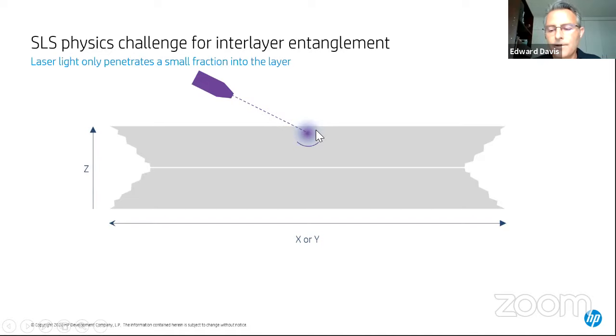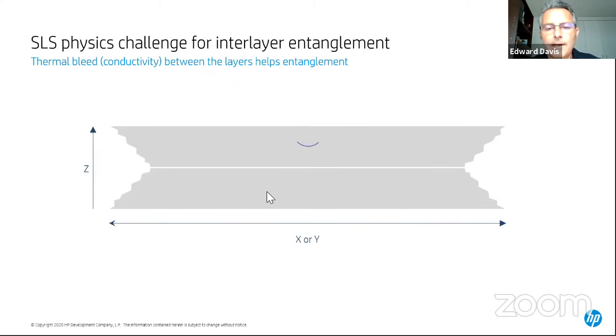Now, the fact of the matter is the laser only penetrates into the layer about 10 microns, and the layer thickness is about 100 microns. And so you literally depend on thermal conductivity to get good bonding between the layers. Now, of course, if you've got this thermal conductivity in the Z direction, because you want good bonding, you also have thermal conductivity in the X and Y.